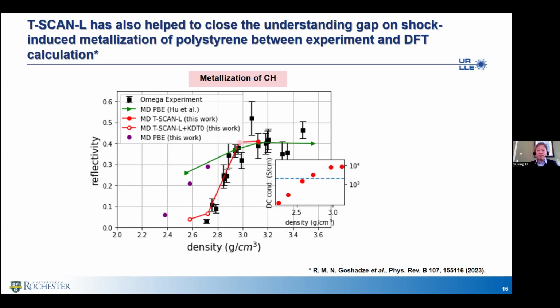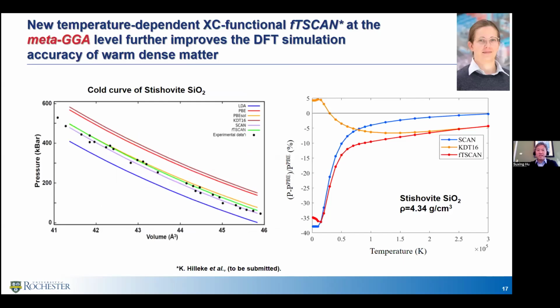And there was one more example. This is Katie's recent work, and she is trying to develop this true meta GGA level of what they call finite temperature SCAN functional. And this is what she applied this functional to, silicon dioxide. What this picture shows is what we call the cold curve, which is a pressure as a function of the volume. And when you get to a high density going this way, you will get a high pressure, of course. This is at a zero temperature.